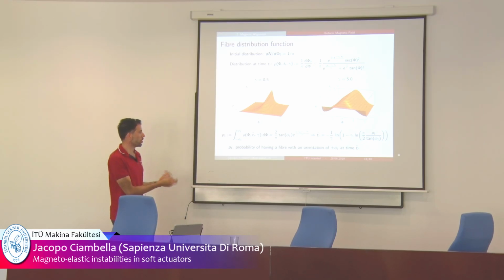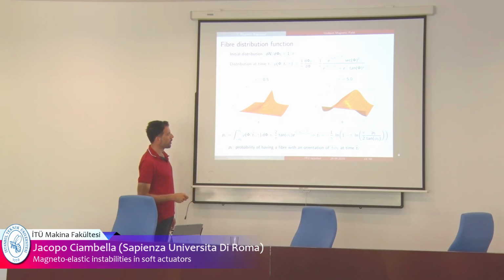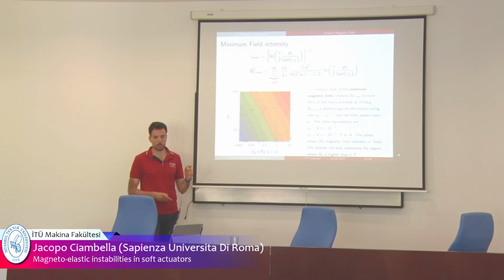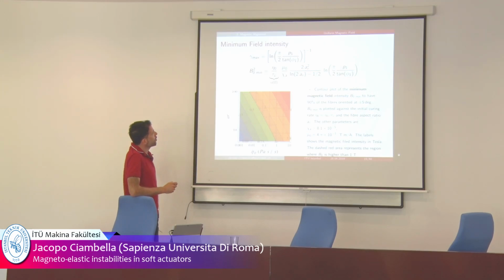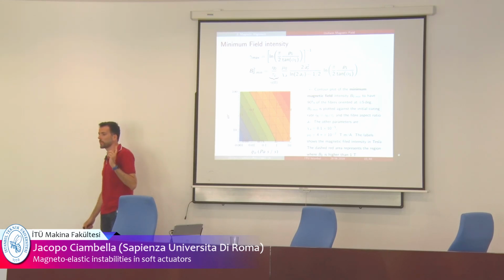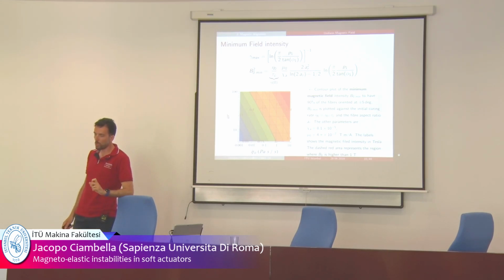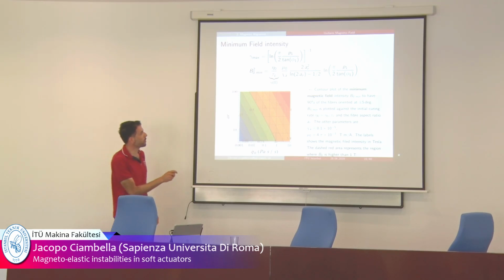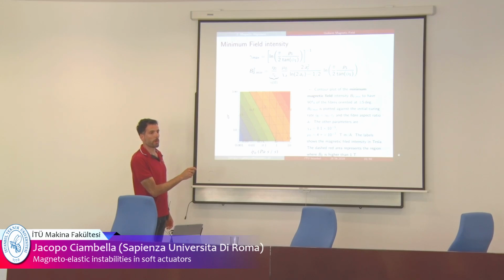Okay, what can you do with this? You can calculate, for instance, the probability of having a certain fiber within a certain orientation in closed form, and this is quite interesting because it is useful to work out this B0 min. That expression gives you the minimum field you want to apply once you know the properties of the matrix. I remind you that eta 0 is the initial viscosity of the matrix and tau c is the curing time.